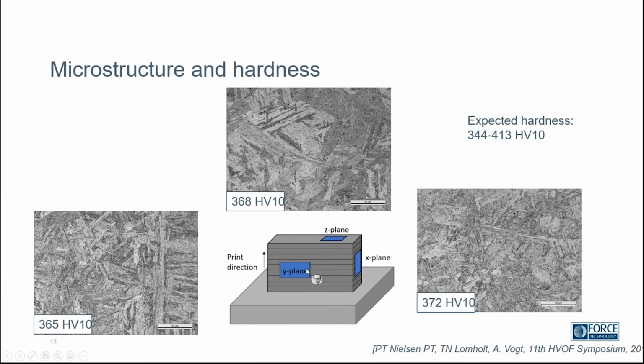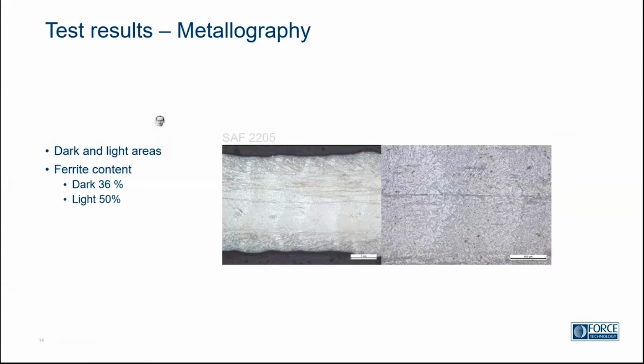Which essentially comes to this, that we are now building up. So perhaps we have the wires, the printing going along this plane and also along that plane, and all in all, this combination of heat input and cooling and heat and cooling will yield differences in the microstructure, and the microstructure is essentially what governs our mechanical properties on the material level, whereas for the parts, it's the design as well. So of course, when we print something, we want to control that it's okay, and because we don't start out with this big mixed pool of molten metal, we get this more layered structure, as we can see here by the indication of lighter and darker bands.